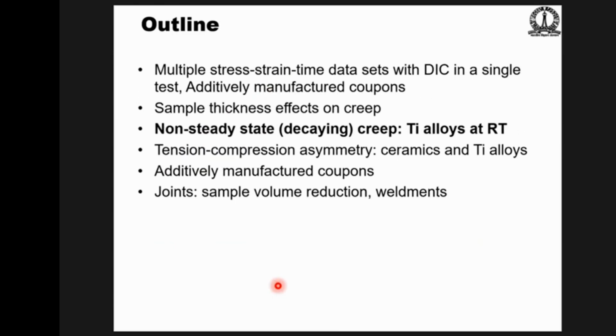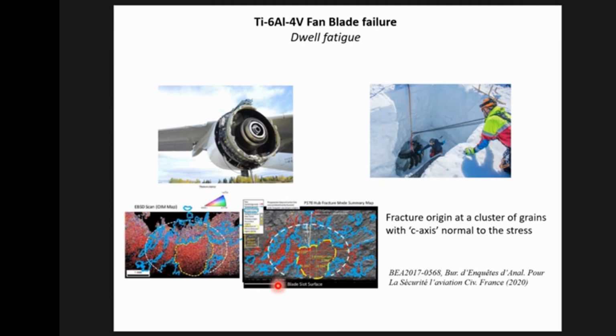So now let me come to the case of titanium alloys, where at room temperature, this is a very unusual phenomenon. Titanium is a very refractory metal, but it exhibits a phenomenon of room temperature creep, which is exacerbated by fatigue. And so this is a very important aspect that contributes to failure. And this is a famous failure. I think it's an Air France plane where the engine fell off. The engine fell off, and this is being recovered from the Greenland ice cap.